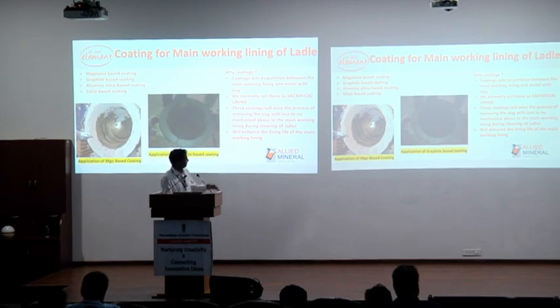So you can easily clean the slag and the dross, whatever is sticking to the ladle, and you can apply the coating again and put the ladle into operation. Whereby you can enhance the lining life of the ladle.